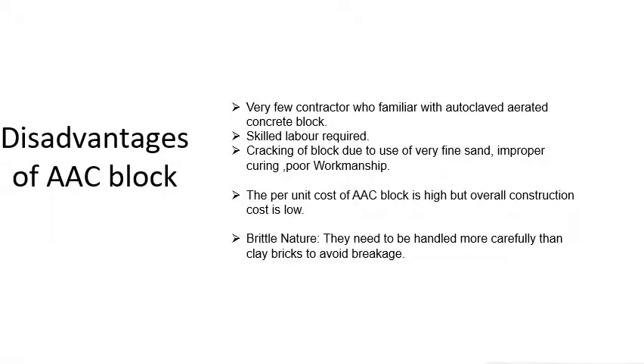Disadvantages of AAC block: Very few contractors are familiar with autoclave aerated concrete; skilled labor is required. Cracking can occur due to use of very fine sand and improper curing. The per-unit cost of AAC block is high, though overall construction cost is lower. Due to its brittle nature, AAC blocks need to be handled more carefully than clay bricks to avoid breakage.